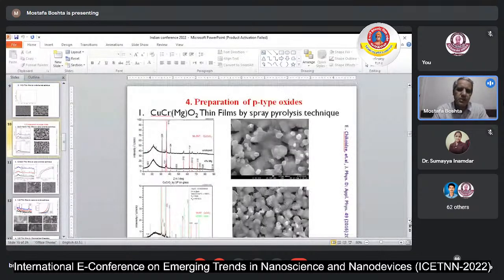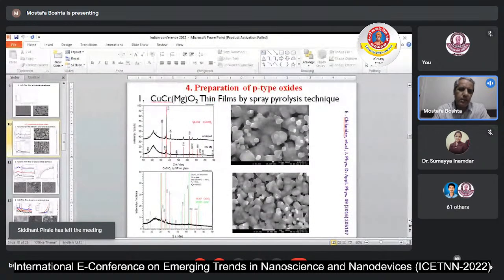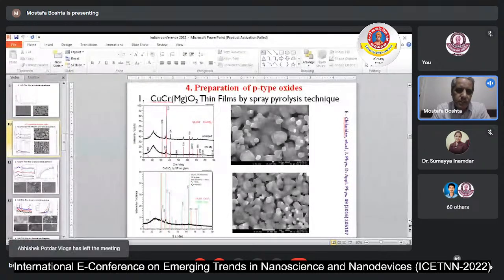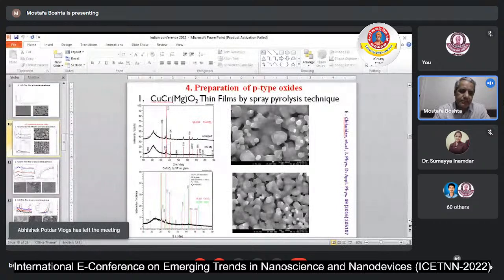After that, we can also deposit in our lab some P-type oxide materials, like copper chromium magnesium oxide, by spray pyrolysis. This material needs more than just direct spraying. It needs two steps to get a crystalline material, because when we deposit by spray pyrolysis, we get an amorphous material, which makes it hard to know whether it is copper chromium magnesium oxide or not. So we anneal this material at a temperature close to 1000 degrees to get this quality and high crystallinity.